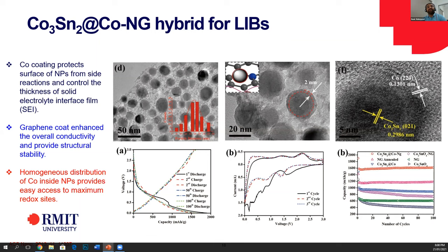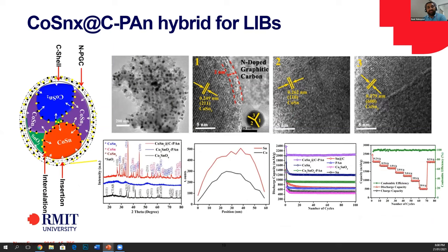So we think that if we need only the surface protection, we can also do this with the nitrogen doped carbon. So we put some nitrogen doped carbon, but we still found that the issue is that the electrolyte cannot go inside, and still some of the materials start breaking. So what we did, we break the particles by itself into different phases.